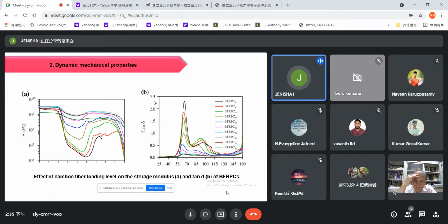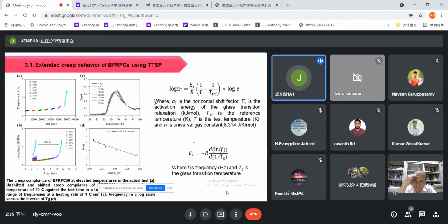Even in this, we could see the trend that we followed in the previous table. That is, till 60 weight percentage, the characteristic feature increases, and then at 80 it decreases. And this is the extended creep behavior observed. So the figure 2a shows the creep compliance with elevated temperature in the actual time for the entire duration, and the B shows the unshifted and shifted short-term creep compliance curves of the composite with weight percentage 60 at temperature tested plotted against the log of time.